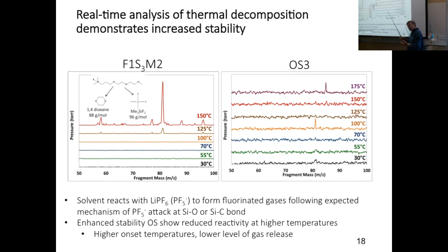And then we make something that's like a little battery. And essentially what we do is we either drive the sample electrochemically and look at what gases are involved, or we simply heat it up and look for evidence of thermal reactions. So at some point, this lithium PF6 will begin to react with the electrolyte, and when that happens, it begins to evolve various degradation compounds.